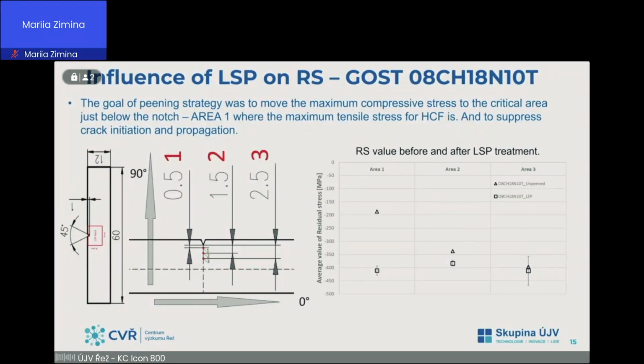Okay, there's a result of analysis of residual stress measuring on specimen for the 3-point bending test, fatigue test. And the goal of peening strategy was to move the maximum compressive stress to critical area just below the notch, area 1. The area 1 is nearby the notch, where the maximum tensile stress for high cycle fatigue is, and to suppress the crack initiation and propagation. The other areas 2 and 3 are farther than the notch.